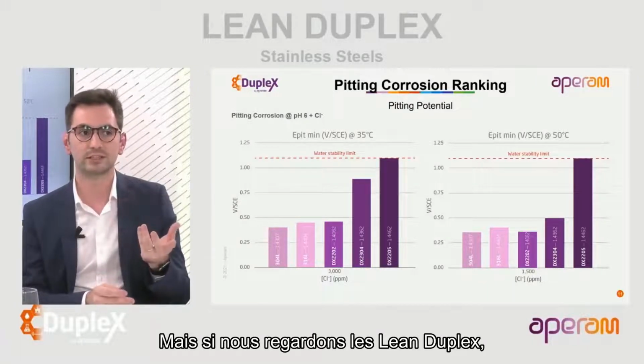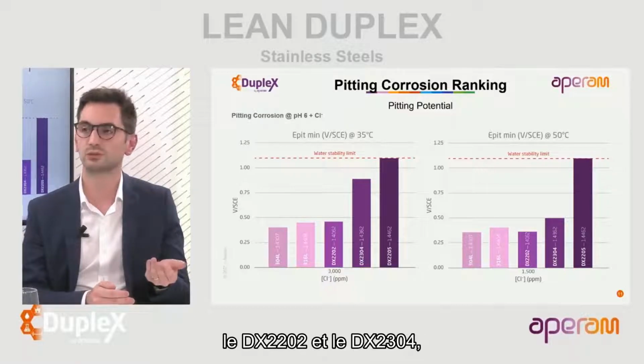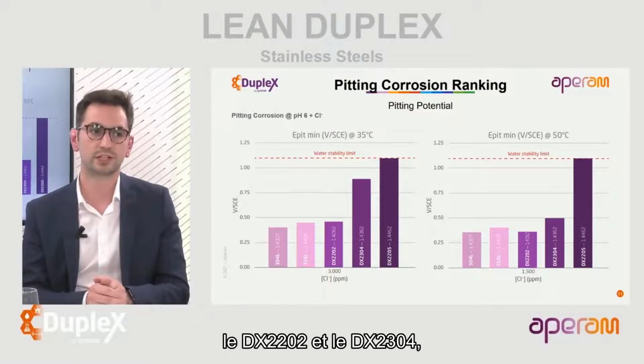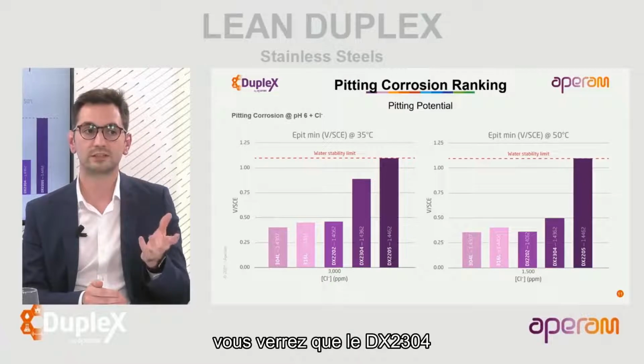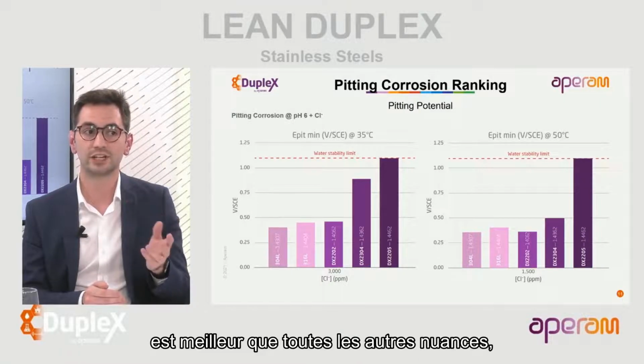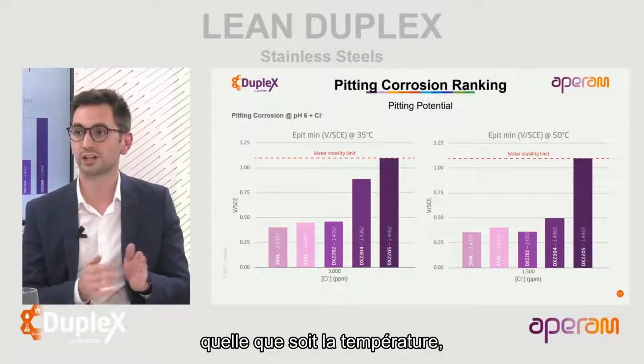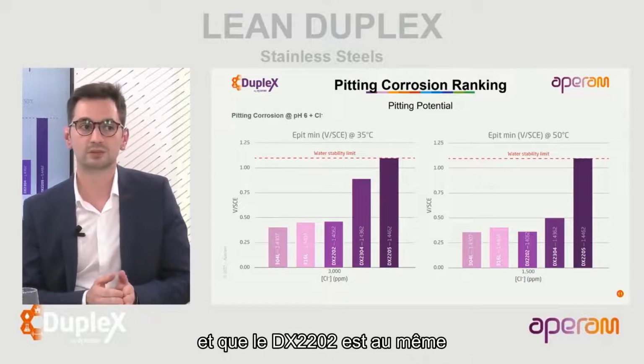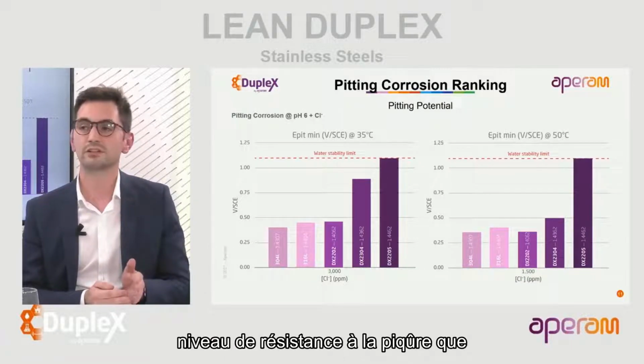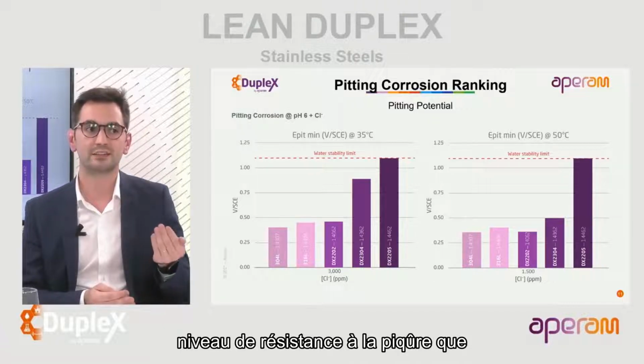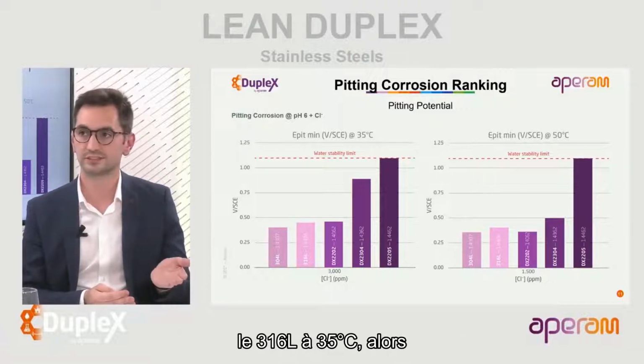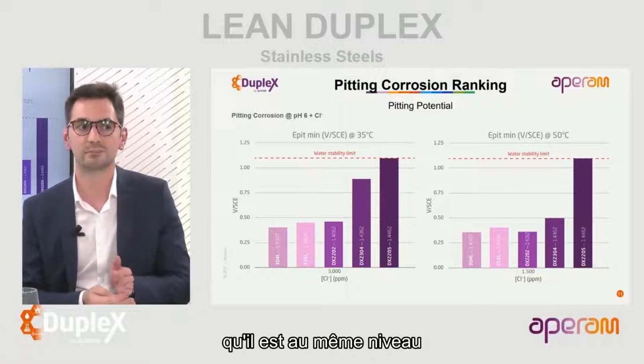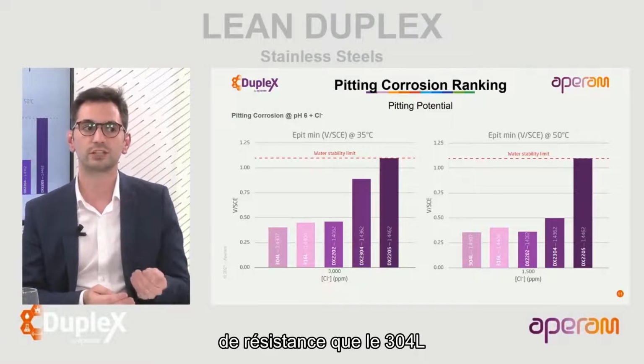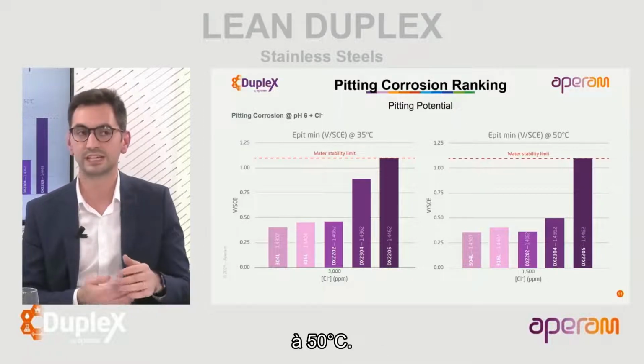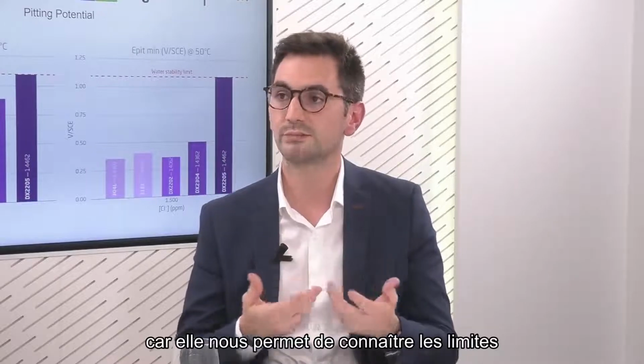But if we take a look at the Lean Duplexes, so the DX2202 and the DX2304, you will see that the 2304 is better than all the other grades, whatever the temperature, and that the DX2202 is at the same level of pitting resistance as the 316L at 35 degrees Celsius, whereas it is at the same level of pitting resistance as the 304L at 50 degrees Celsius. And that's very important information because it allows us to know the limits of the material.